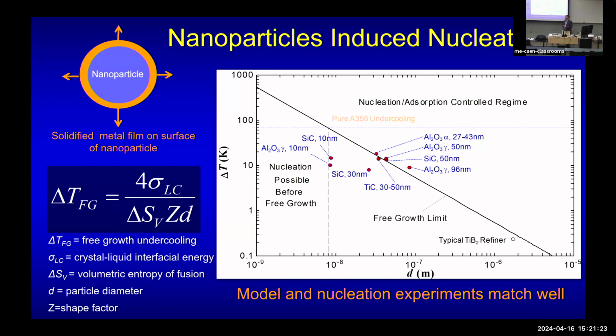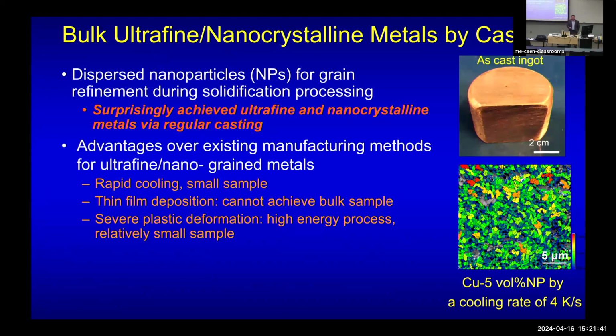That's why around 2005, 2008, after the PhD graduation, we thought, oh, we quit this direction because we cannot win. Because to win, we need more undercooling, which means we need more demanding processing conditions to enable that. So until 2015, we finally solved nanoparticle self-dispersion, and we came back to study the nucleation phenomenon. We found, surprisingly, something really unusual happening here.